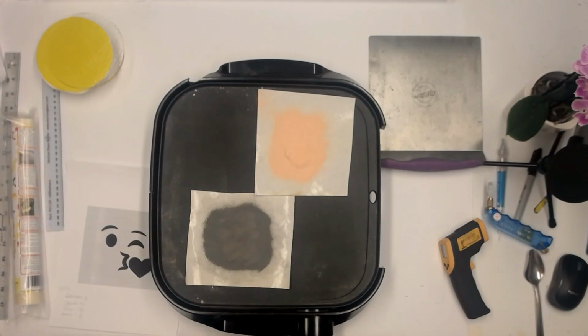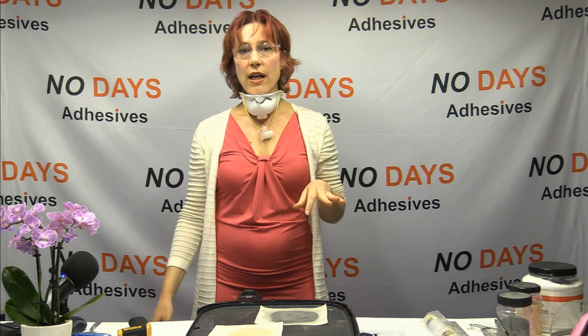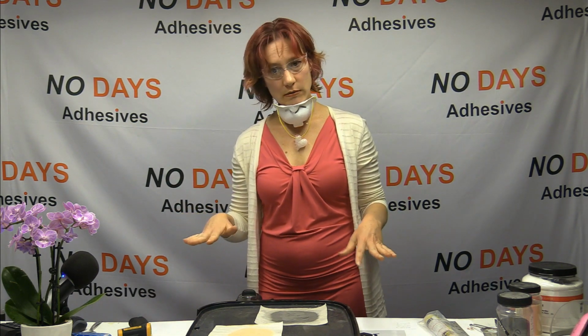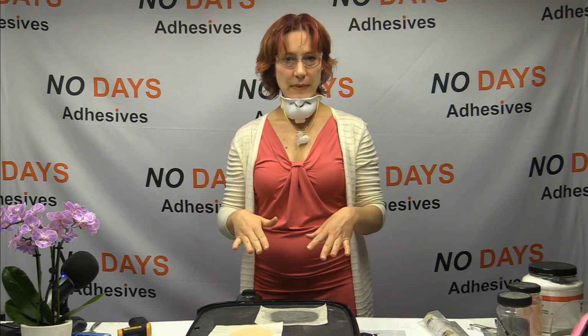If you end up leaving this on the griddle for too long, the powder is actually going to deform. The edges aren't going to be as crisp. It kind of starts to just ooze out into the layers of the powder, so you get not crisp edges, basically, right? So we don't want to leave that on there for too long. It's not something that you want to do and then walk away and do another task and forget about. This is something that you want to do and then maybe tidy up a little bit while you're doing whatever you're doing, and then come back to it.